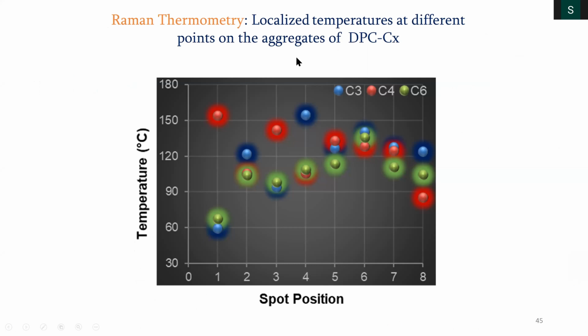So by using this, we measured the temperature, and we observed that one can go up to 150 degrees Celsius by simply exposing with light. Now you will say that the previous reaction that I was doing was at 400 degrees Celsius, and the temperature I'm getting here is 150. So ideally, I cannot use this system.